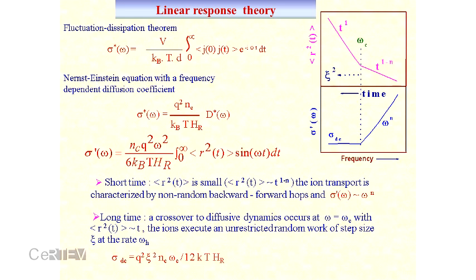So there is a jump from DC to the dispersive region according to linear response theory, at least qualitatively, but the jump is sharp. Experimentally we have observed that the change is very gradual, and the very gradual dispersion gives us some idea about the relaxation mechanisms.